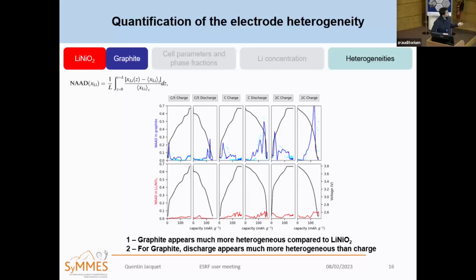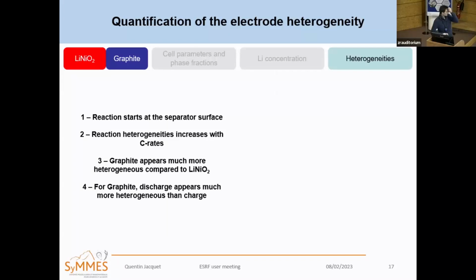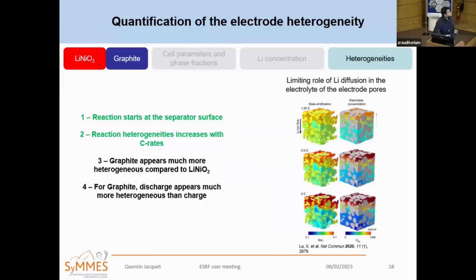And the second thing you can see is that for the graphite especially, the charge seems to be less heterogeneous than the discharge, and that is true for C and 2C. So now if we take all of these observations and try to understand if they make sense or compare them to the literature, well, the first two, that the reaction starts at the separator surface and the reaction heterogeneity increases with C rate, is fairly well described in the literature.